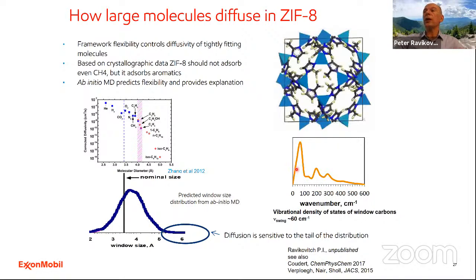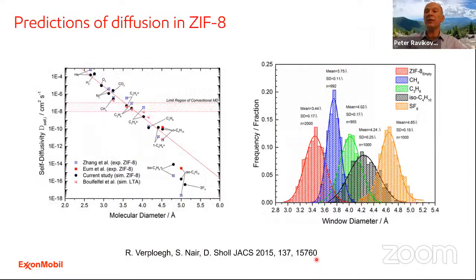But as I mentioned before, another factor is the coupling between the flexibility of the framework and molecular diffusion. And this coupling is shown very nicely here. This is work of David Sholl's group, where they simulated diffusion of a range of molecules in ZIF-8, and they used transition state theory. As you can see, these are the histograms of the window sizes in the transition states when the molecule is diffusing. The window is expanded temporarily, but this expansion is very substantial and bigger than for zeolite.